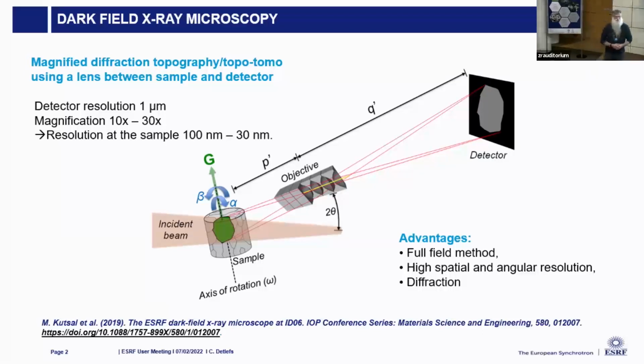But also the objective acts as a pinhole in the diffracted beam. So with that, we actually gain quite high resolution in the scattered beam directions, which is not the case for typical X-ray topography, where you have a detector in the near field and you basically have very little resolution in the scattered angle and then in the transverse direction. It's a full field method. It's non-destructive. And because it's non-destructive, it can be used in situ to follow processes as they go along.